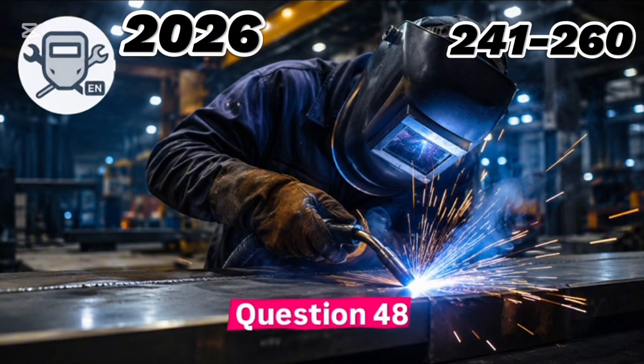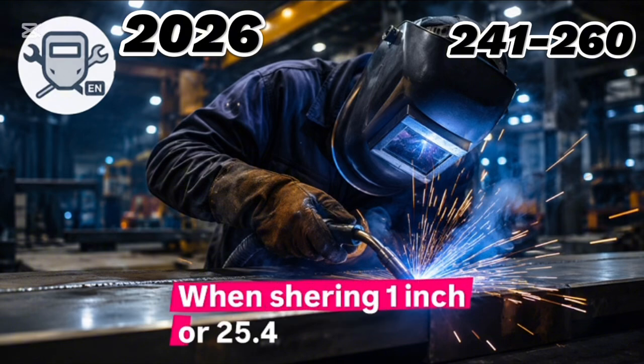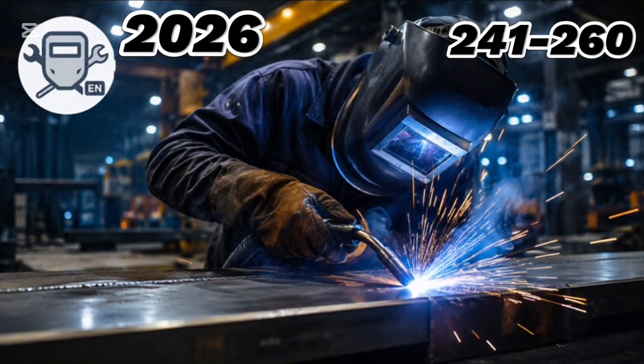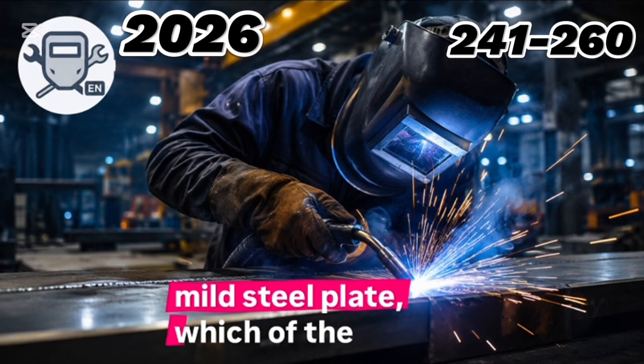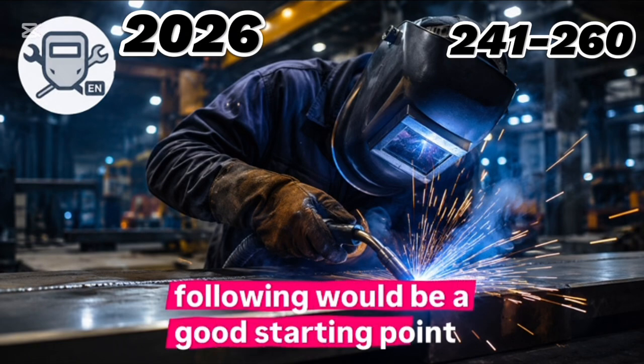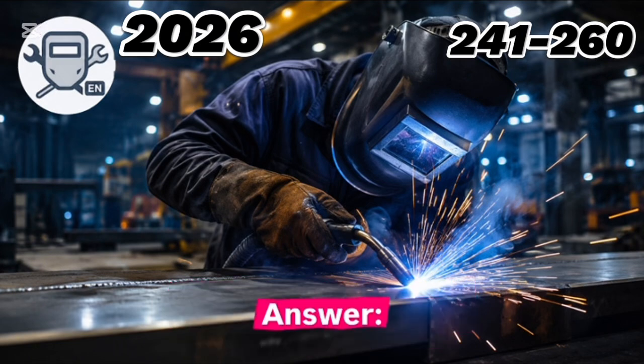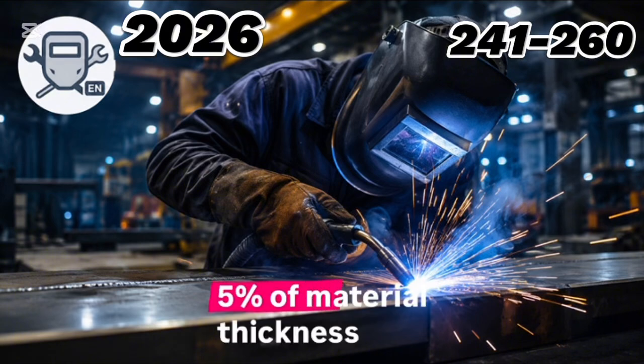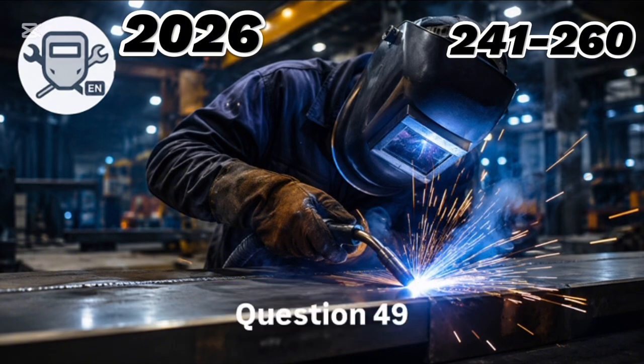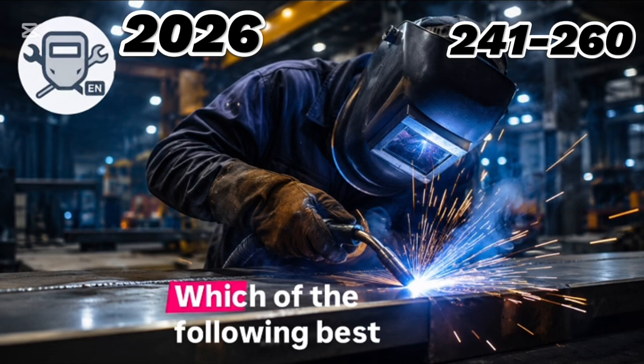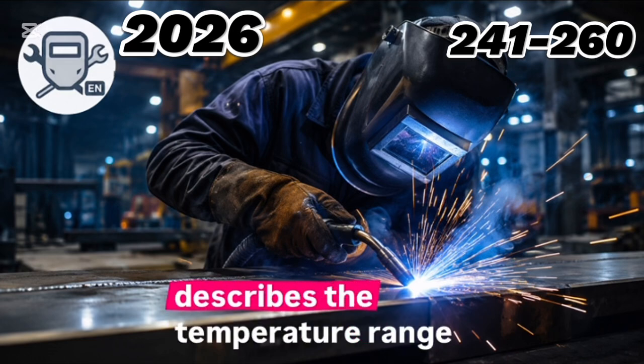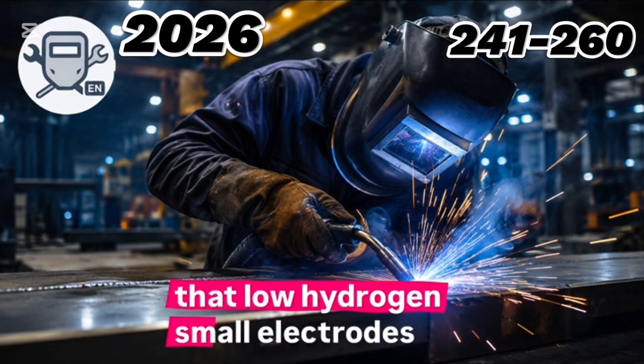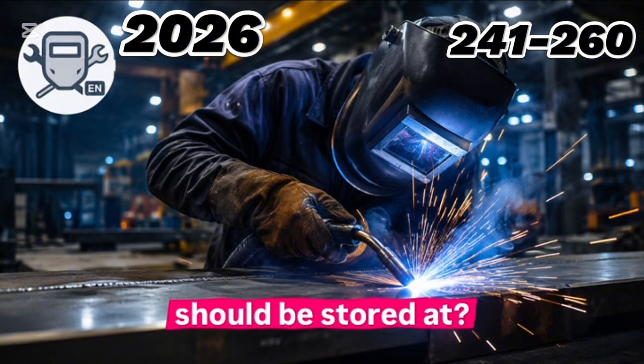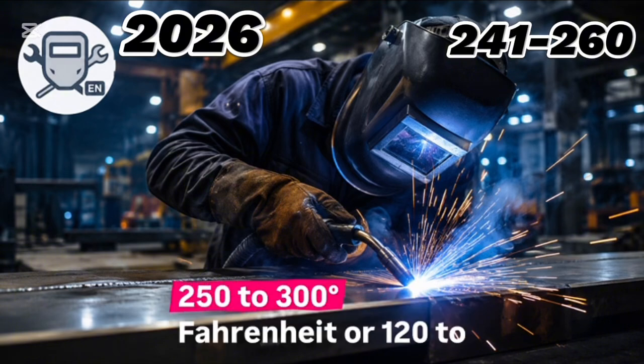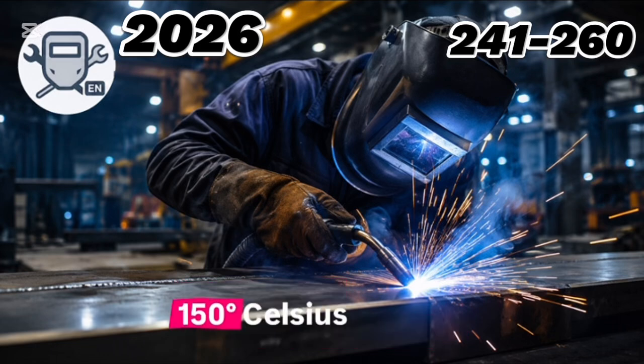Question 48. When shearing 1 inch or 25.4 millimeter mild steel plate, which of the following would be a good starting point for blade clearance? Answer: 5% of material thickness. Question 49. Which of the following best describes the temperature range that low hydrogen SMAW electrodes should be stored at? Answer: 250 to 300 degrees Fahrenheit or 120 to 150 degrees Celsius.